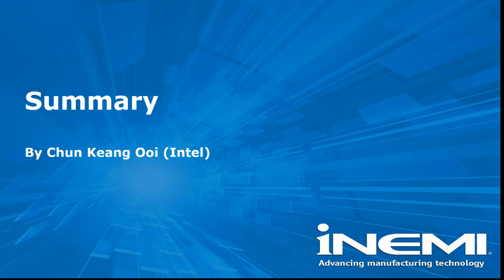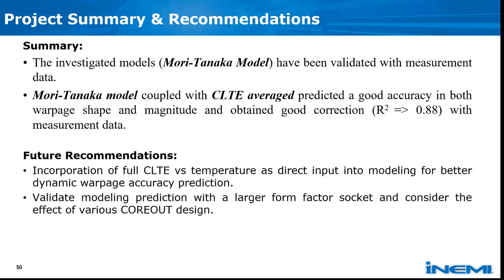Thanks, Philip, for the good sharing on the results and the discussions. So now I'm going to close the summary for this phase 2 project. So far, what has been shared and investigated with this new model, the Mori-Tanaka model, is that we have compared and validated against the dynamic warpage measurements. We also investigated this new model with the CLTE average input method, and found it provides a good correlation for both room temp and high temp warpage data. Coupling this new Mori-Tanaka model and the CLTE average approach, we're able to obtain a good correlation, which means R squared is greater than or equal to 0.88 with the measurement data.